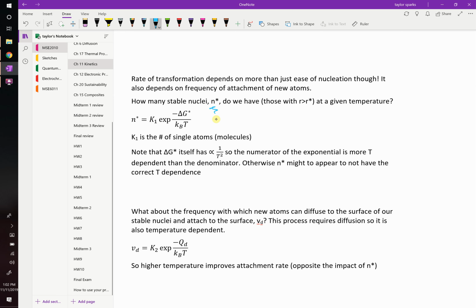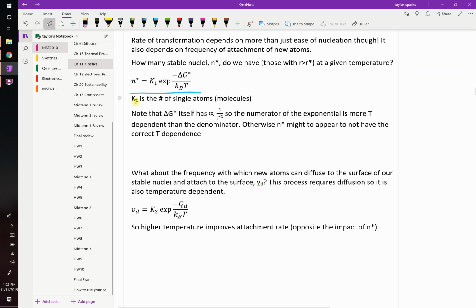We have an expression for it, and it is Arrhenius, right? N star, the number of these nuclei, is going to be equal to a constant K1 multiplied by the exponential of the activation energy for nucleation divided by your thermal energy, okay? So at any given temperature, you could plug in T there and figure out how many nuclei should I have. Is it 1 or is it 1,000,000 or what is it? And this will spit out a number, right? Okay. You do have to know the constant K1, which is going to depend on your system ahead of time, okay?